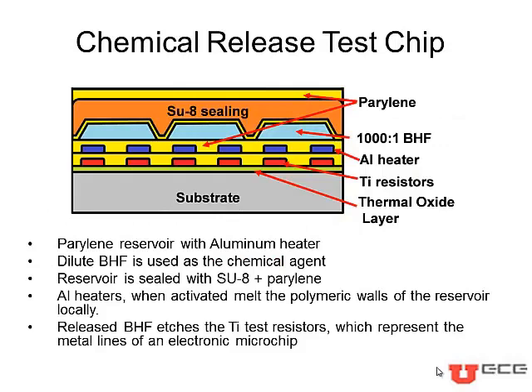To test all these ideas, we fabricated a test chip. It consists of a substrate wafer, which can be either glass or silicon, with titanium test resistors patterned at the surface. The titanium test resistors are indicators of the chemical attack on the chip. On this test substrate, we fabricate the microfluidic plane. The bottom wall of the reservoir consists of a layer of Parylene and embedded aluminum heaters. The reservoir is filled with a 100 to 1000:1 dilute solution of BHF, which etches both the silicon dioxide passivation layer and the metal lines. Finally, the reservoir is sealed by a layer of SU8 and Parylene.